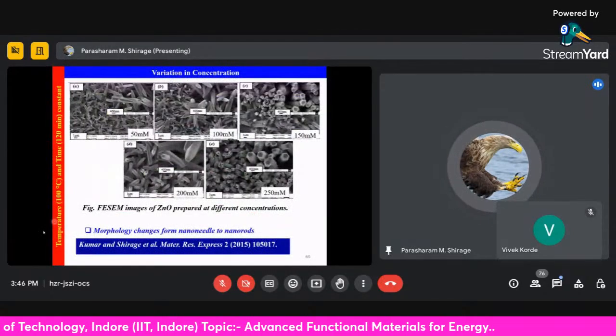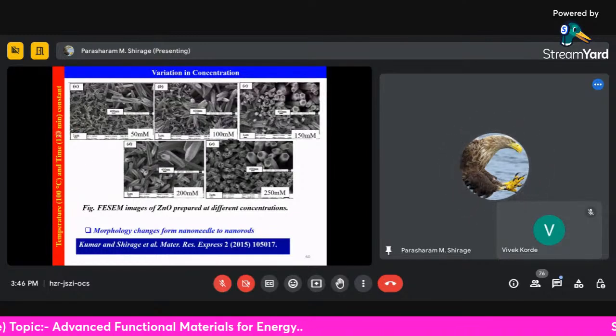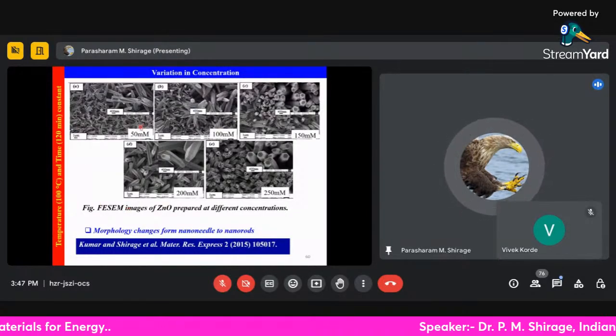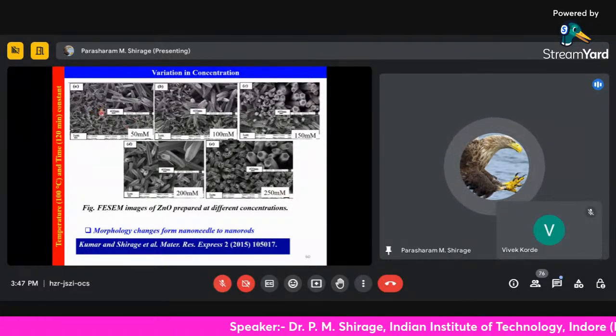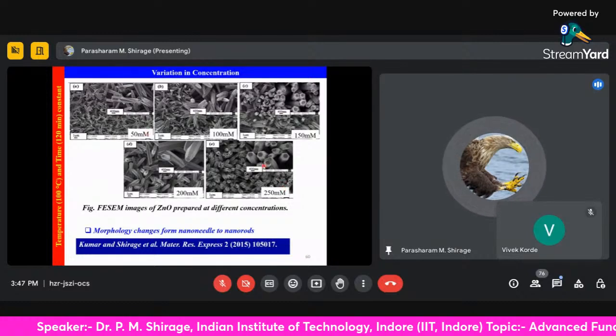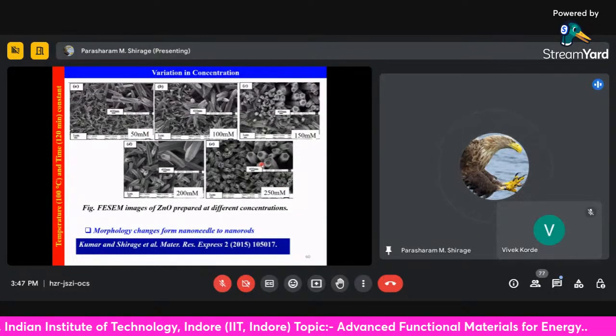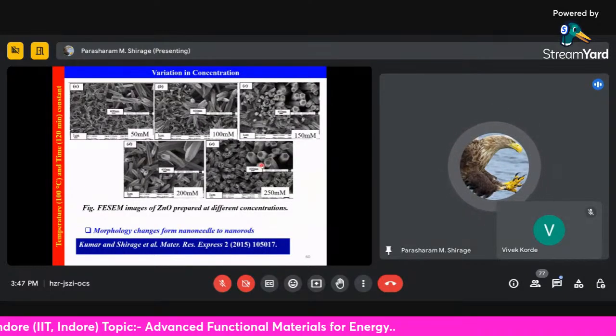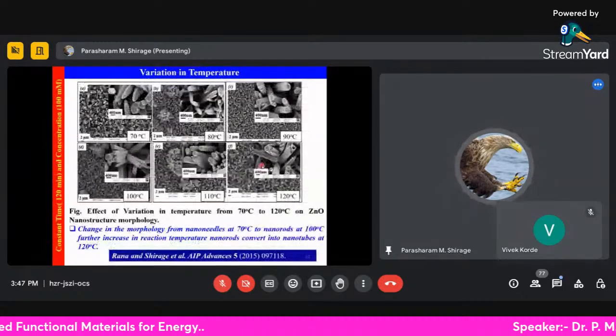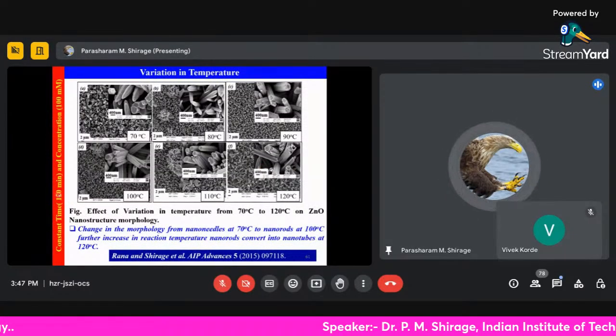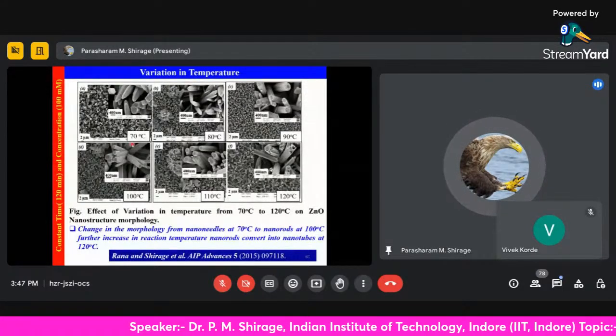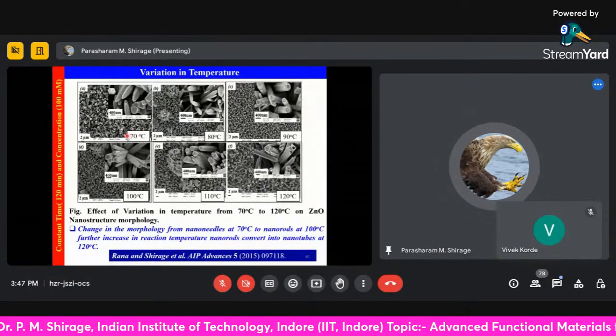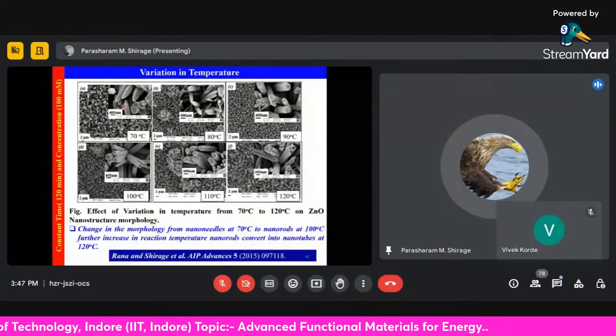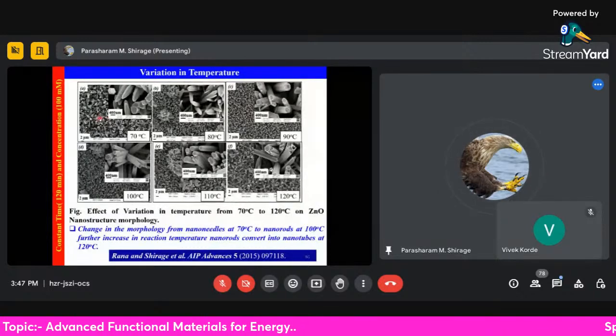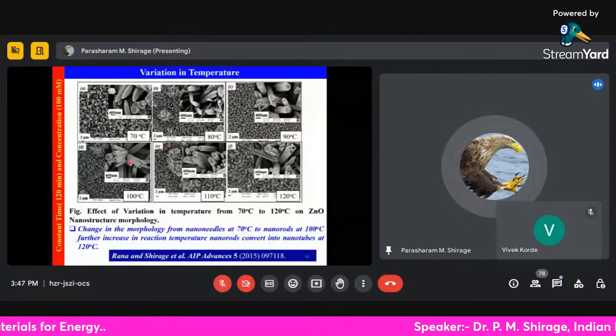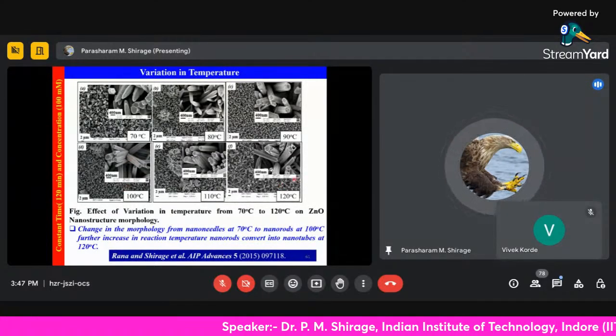For example, if I keep the temperature at about 100 degrees centigrade and the time at 120 minutes constant, and if we change the concentration from 50 millimolar to 250 millimolar, then you can see this needle-like morphology on the microscope change to a tapered needle-like structure. Its dimension is also increasing. So if we keep temperature and time constant and change the concentration, its morphology changes. Then if we keep the time at 2 hours and concentration at 100 millimolar, and change the preparation temperature, like 70, 90, 120 degrees centigrade, you can see needle-like morphology formed at 70 and 90 degrees centigrade. This is forming a rod-like structure, and at 100 degrees centigrade completely rod-like, and at 120 degrees centigrade this is a tube-like structure.